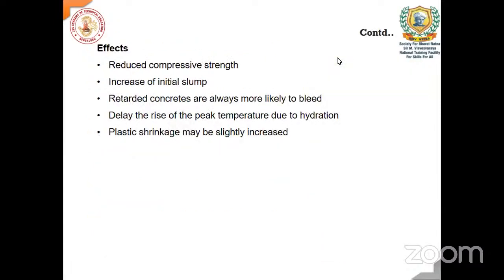Then the effects: care must be taken, otherwise we'll end up with reduced compressive strength. Then it may increase the initial slump. See, the main objective is to keep the concrete workable for a longer duration. Because of this, the initial slump may be high. See, what will happen when the water is not consumed in the hydration process and the free water is still available, it may lead to bleeding of the concrete. These are all the unwanted effects of the retarders. So that is why care must be taken.